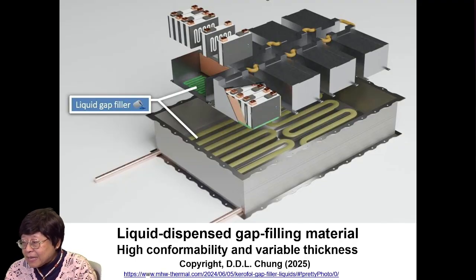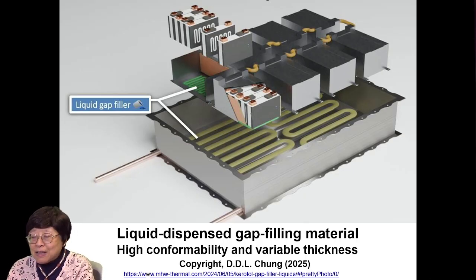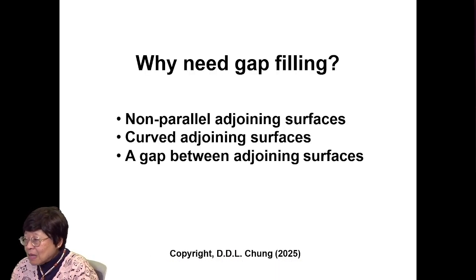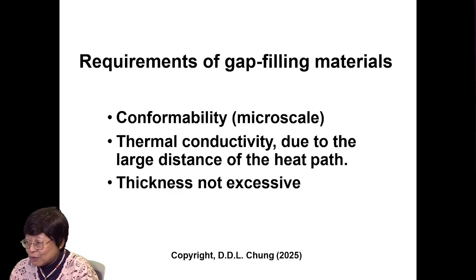And liquid dispensed gap-filling materials, like here, like a snake, give high conformability and variable thickness. However, the gap between adjacent lines of this pattern are not attractive, because the empty spaces would be just air, which is a thermal insulator. Now, why need gap filling? Non-parallel adjacent surfaces, curved adjacent surfaces, even a gap between the adjacent surfaces.